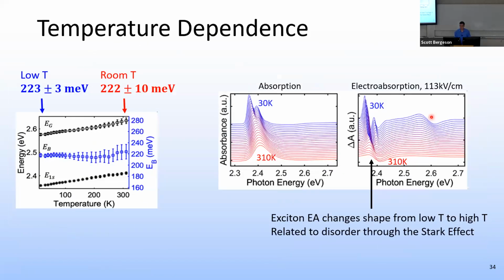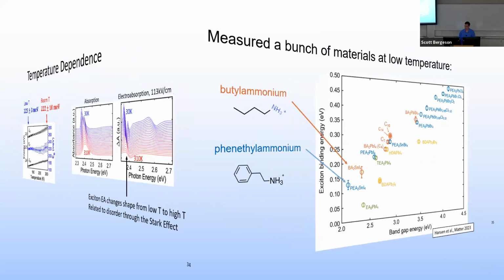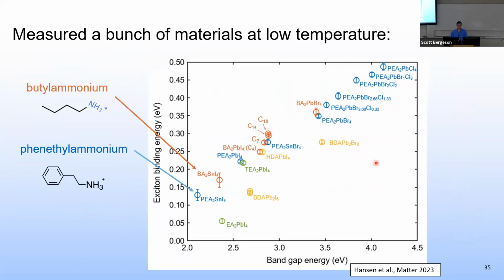We can also look at temperature dependence, and we see a change in the electroabsorption line shape going from low temperature to room temperature. This is related to disorder through the Stark effect, but unfortunately we don't have any time to talk about that. But what we did was measure just a whole bunch of materials, just anything that we could make, and then measured the band gap energy and the exciton binding energy for all of these materials. And you can see a clear correlation between the two. And this was something that was thought to exist, but nobody had really seen before. So this is new. But we were able to go even farther than that.